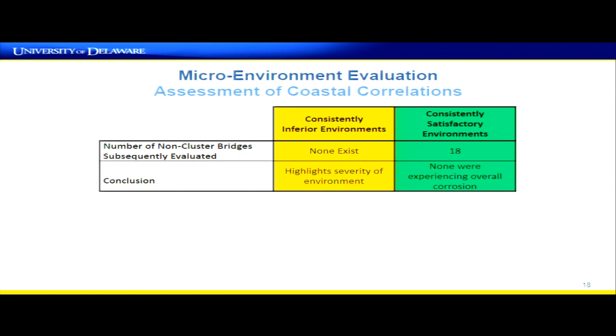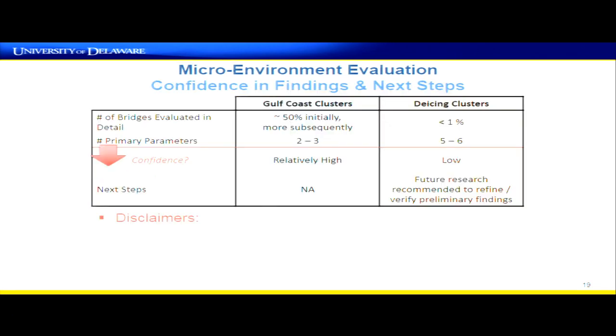For the consistently satisfactory environments, we looked at 18 other bridges, and all of those were performing well. So when it comes to the coastal clusters, we feel like we've looked at a large percentage of the bridges in that area, and we have relatively high confidence that those environments are good for giving owners some quantitative guidance about what a coastal environment is. For the de-icing clusters, we've only looked at about 1% of the bridges within that environment, so there's low confidence to really apply those numbers. Our next step there is that we've recommended future research to look further into that.